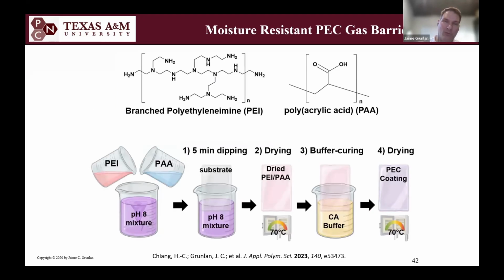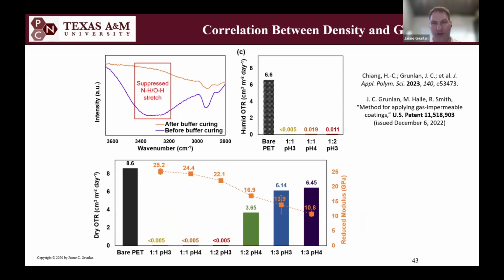More recently, we took those same two polymers, but we made a polyelectrolyte single solution and then just dipped a piece of PET into that solution, and then once again cured it with the citrate, just like I did with FR. It makes a 1 or 2 micron thick coating, and it's undetectable if I have the correct ratio of the two ingredients and I cure at the right pH. So that's kind of cool. So we got rid of all the processing steps and just made this really nice, clean, transparent, high barrier polymer coating. And it was so cool that we thought we should try to patent it, and we did, and it was issued, so that was terrific.